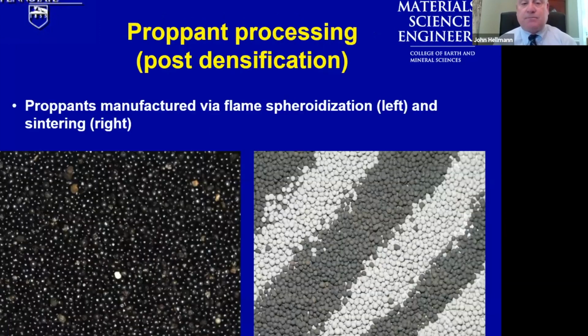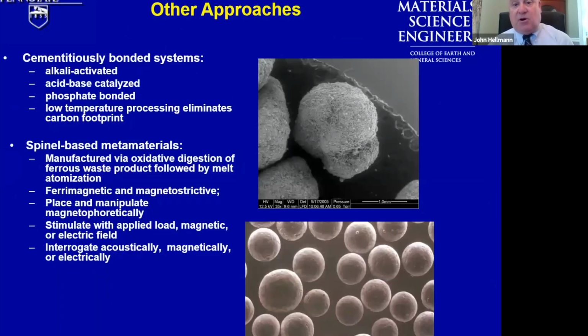metabasalts and andesites. So the proppant processing technologies that we've developed work with drill cuttings. On the left, you see vitrified beads made by flame spheroidization. On the right, you see commercial proppants manufactured via sintering. There are other approaches to densifying these materials. Cold sintering and cementitiously bonded systems both work. We've demonstrated in other work that we can achieve moderate strength particles from some of these raw materials without requiring sintering cycles. Hence, no use of hydrocarbons, no production of CO2.